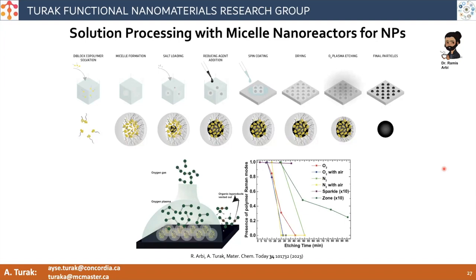Right, so the other thing to keep in mind from a nanoparticle synthesis perspective, the thing that's very different about using reverse micelles, and the reason we think about it like a reactor, is that in traditional ligated synthesis, the ligands are permanently attached to the surface of your particle. That's why when you remove the ligands, you end up with lots of defect states. In this case, the particle will often form in situ inside the micelle and then detach itself, if it is attached at all, from the ligands. So the ligands form this balloon shell, but they're not physically anchored to the surface, either through electrostatic interactions or sometimes even osmotic pressure that forces the precursors to go inside the micelle. That means that whatever defects are happening are there before you form the structure. So that gives you a lot of tunability and control. But the main way that we remove it then is to use some oxygen plasma and other kinds of plasma to attack the polymer and remove it from the surface.